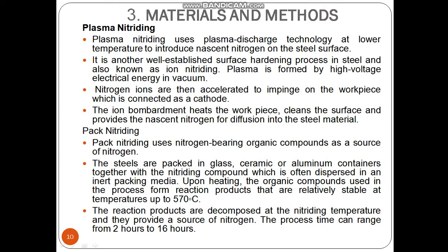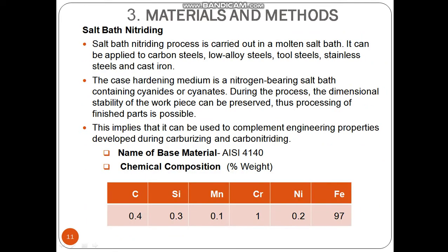Pack nitriding. Pack nitriding uses nitrogen-bearing organic components as the source of nitrogen. The steels are packed in glass, ceramic or aluminum containers together with the nitriding compound, which is often dispersed in an inert packing media. Upon heating, the organic components used in the process form reaction products that are relatively stable at temperatures up to 570 degrees Celsius. The reaction products decompose at the nitriding temperature and provide a source of nitrogen. The process time can range from 2 hours to 16 hours.